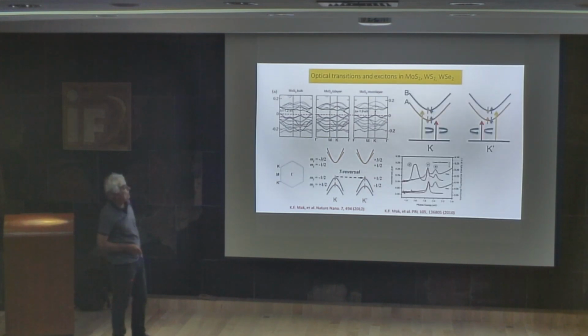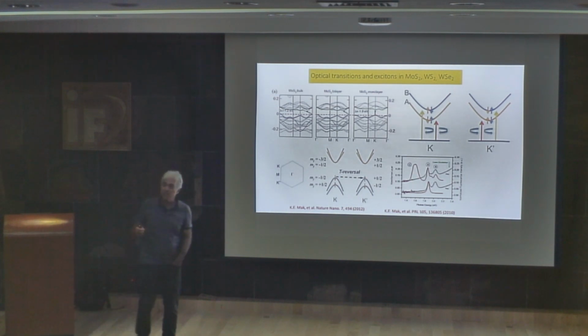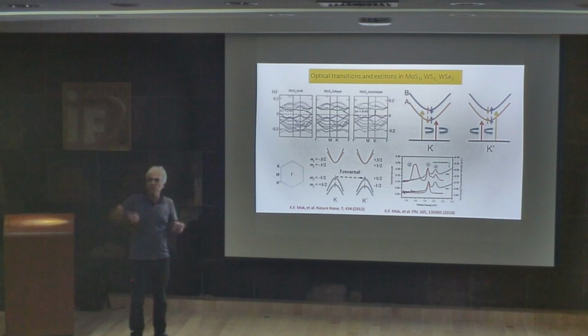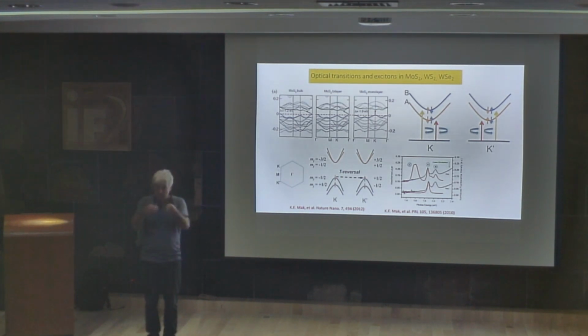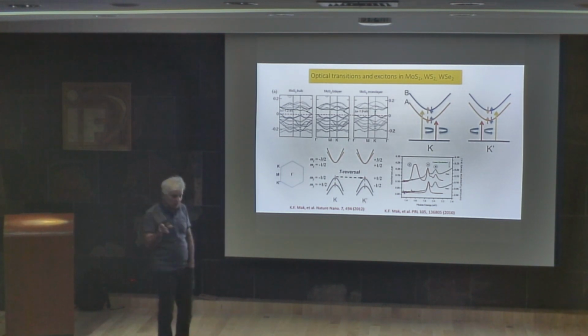And another important thing is that now, in the case of 2D materials, when I have one excited electron and leave one hole, the electron and the hole are in the same layer. There is a very strong Coulombic interaction between the electron and the hole. Then when we have this bound electron-hole pair, because they are interacting, we have what we call an exciton. An exciton is one bound electron-hole pair.